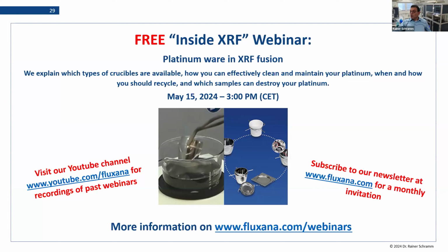Another question. On platinum ware on the outside of the crucible, what can be causing a blacking of the metal that eventually ends up cracking from outside? There I have no idea so far. Perhaps you have to be careful when you take a hot platinum and you put it on any surface in your lab. If this surface is not pure refractory material and it's perhaps a metal plate, it could of course attack the platinum from outside. Otherwise, I have no idea so far.